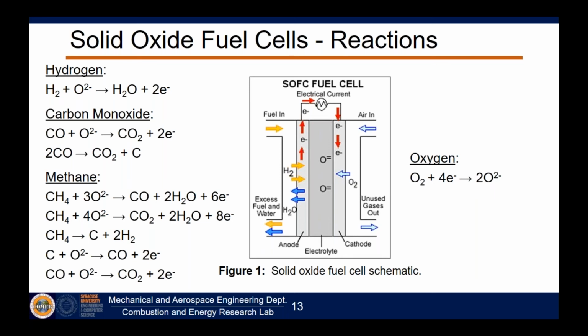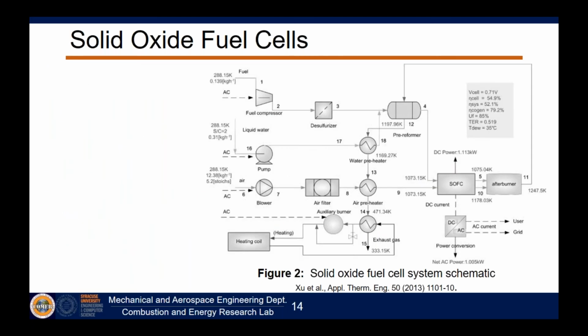And you look at this slide and you say, this is kind of complicated, but that's kind of the point. Here's the fuel cell, and here's everything else that you need to actually make this happen. The system's fairly complicated, actually. What you need to do is take air and fuel. We typically desulfurize the fuel because sulfur also has some issues with the anode materials, similar to the carbon deposition problem. We then supply water, bring it up to temperature so that it forms steam, and then we use that steam in what's called a steam reformer for these steam reforming reactions. And so even though we can use methane and carbon monoxide, we generally find that hydrogen has much faster kinetics.